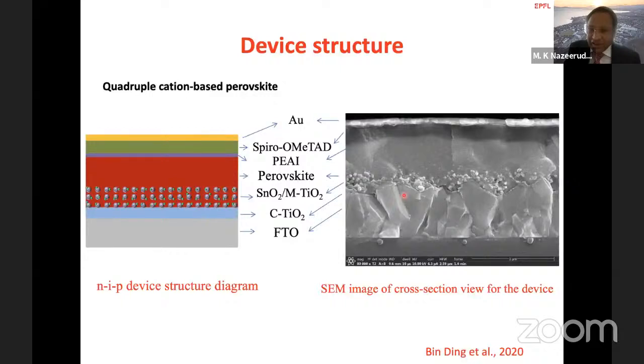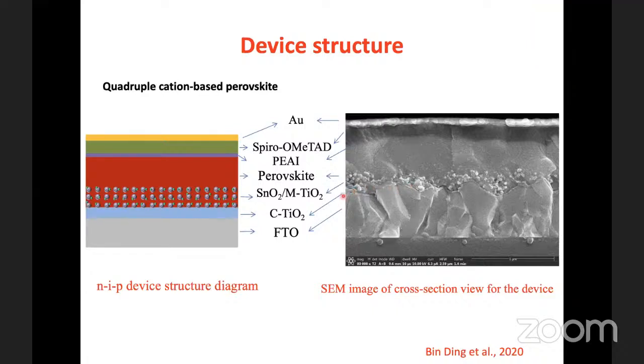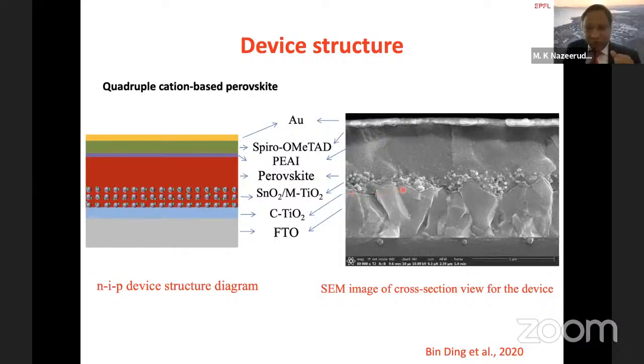Now, coming back to the device configuration, on the left side is a cartoon, on the right side is a cross-sectional image of our solar cell. So what we have is a conducting glass deposited with a compact layer of TiO2, followed by, can you see my cursor? Can you see the laser pointer? Yes. Okay, so we deposit a compact layer of TiO2, then followed by a mesoporous layer of TiO2 and tin oxide. It's a bilayer configuration. Then we deposit perovskite in the range of 600 to 700 nanometers thickness.